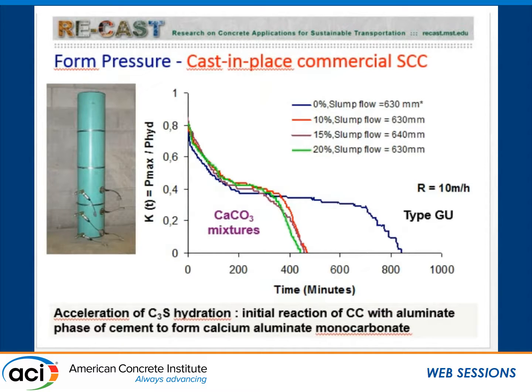One thing that was very interesting is the form pressure. So when you are constructing with SCC, you cast concrete fairly fast because it's a liquid pressure. You assume it's liquid pressure. So this is a sacrificial column that we cast. It's 1 meter or 3 feet. We have some sensors. We can pick up the pressure, and this is the pressure at the very bottom. See the casting rate is 30 feet per hour, so it's very, very fast. And then the initial pressure that is exerted is 80% of the equivalent hydrostatic pressure. So this would be 25 kilopascal. This is 20 kilopascal pressure.